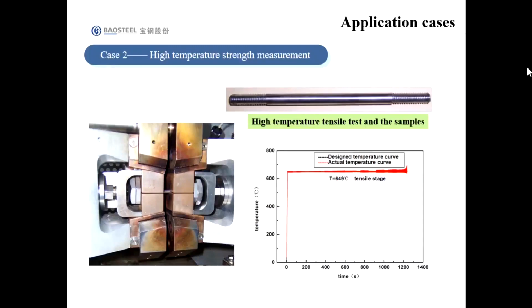Next up, we talk about case 2. Case 2 is to measure high temperature strengths of steels. The actual temperature curve performed by the Gleeble system is in good agreement with the design. The sample for high temperature tensile is shown in this picture.